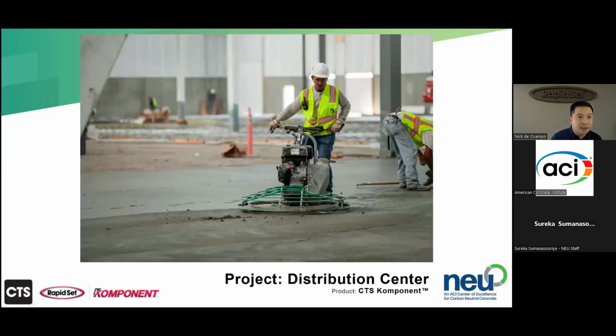My last slide, as I come up on time, is a distribution center where Komponent was used to overcome negative volume change. Again, this is another example of a floor where they extended construction joints to 150-foot spacing, and they didn't have to saw cut any of those, which minimized the amount of dust and worker exposure on site. So that Komponent floor, being close to dimensionally stable, was able to have those extended construction joints and will have minimal repairs going forward.